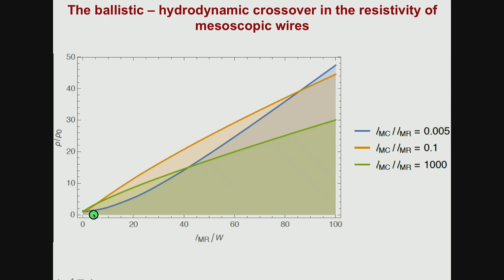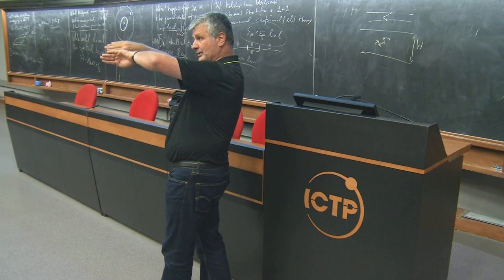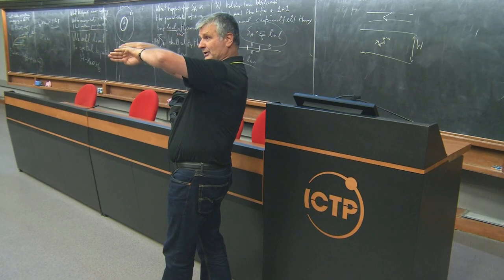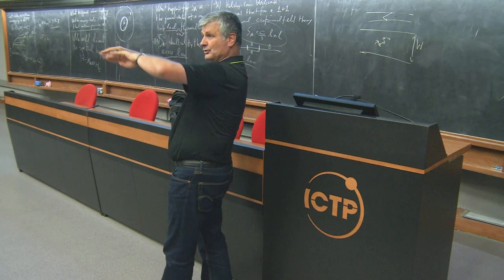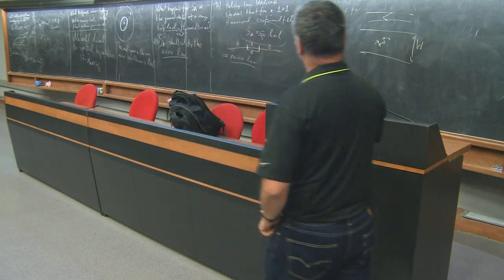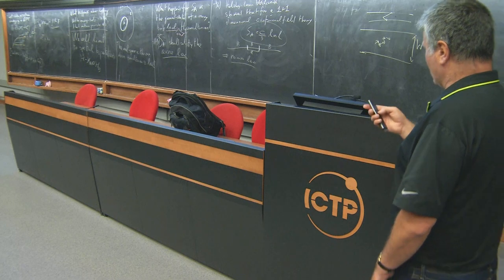And the ballistic one does 2 things. It's higher than the hydrodynamic prediction for relatively wide wires, when W is quite small. And then it crosses to be lower than the hydrodynamic prediction at very narrow wires. And before anybody asks that, that's because in a narrow wire, you will always have some electrons which are just going straight along the wire. And if they're going straight along with a very long mean-free path, they short out the others. So we thought we'll try that type of experiment.